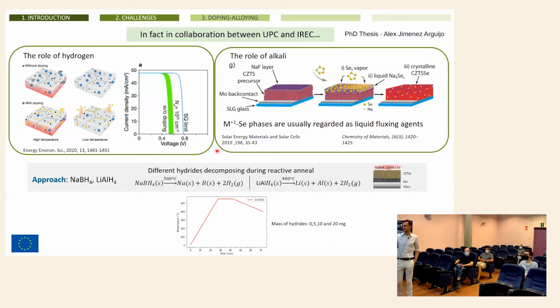So normally the process for synthesizing kesterite is you deposit on a glass substrate coated with molybdenum, copper, zinc, and tin. Elemental copper, elemental tin, and elemental zinc, using sputtering or using evaporation of the metals. When you have this precursor that is only metal, you put it in a semi-closed graphite box. And in the graphite box, you introduce your chalcogen, sulfur or selenium, or a mix of both. And then it's introduced in a tubular furnace where you perform your thermal routine to synthesize and crystallize kesterite.